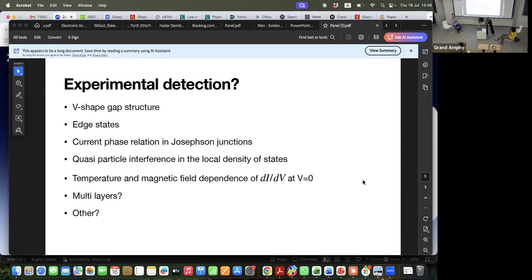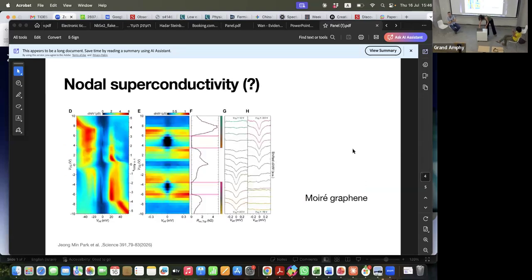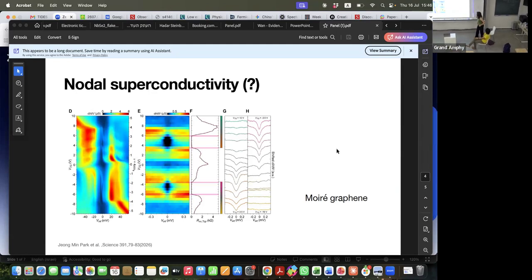Actually, the scale doesn't make sense at all here, right? Delta is huge. Here, this measurement? No, this is not delta. I think their gap is about 0.1, about 200 microvolts, that's 1 Kelvin. That's reasonable. No, but I thought the other was much bigger. I actually don't remember off the top of my head what delta people measure. But the experimental observation is a non-conventional superconductor, so the ratio between delta and Tc is not what you expect. Not 2, but more like 10.